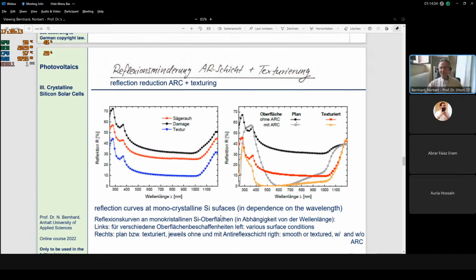Okay, I can also explain it. So the black one is the same as here on the right-hand side, or a similar one, just without any treatment. And then with anti-reflective coating, we would get the black curve. This point would be precisely the point where the lambda quarter condition is fulfilled. That means where the lambda quarter condition is fulfilled, we really have reflectivity 0, but this of course is only possible for one single wavelength, in this case roughly 600 nanometers.